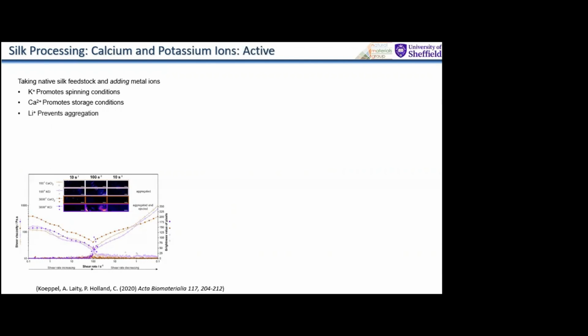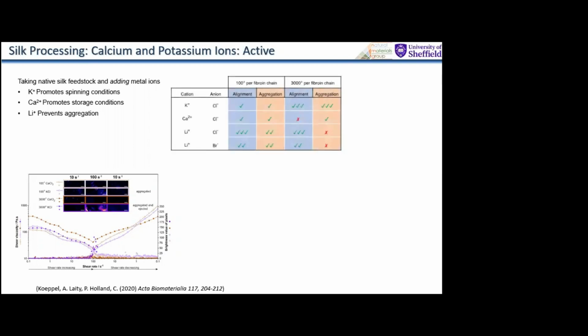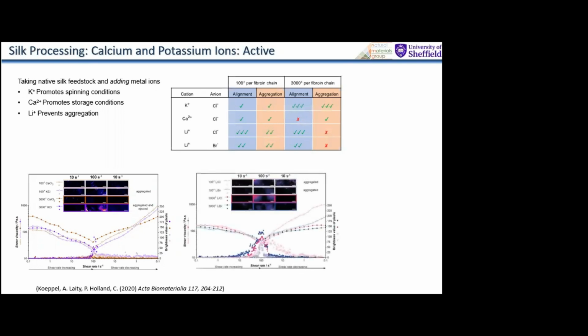Calcium basically promotes storage. So that original high level of calcium promotes storage, and it didn't really spin when we started to flow it. Lithium prevents aggregation. So that was an interesting side that we went into that I can get into a little bit later. But ultimately what we found is that just by changing the metal ions, we were able to change the flow responsiveness of the silk.